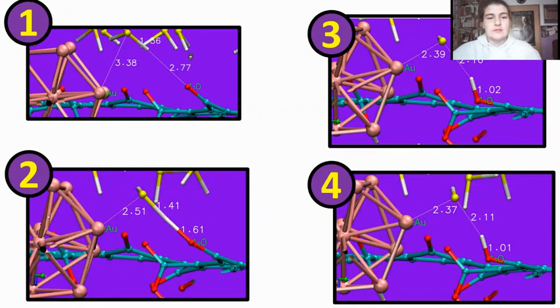Here are the snapshots from the movement. And so you can see that the bond between the sulfur and the hydrogen gets longer until the hydrogen bonds with the oxygen. And this is a very interesting transition, which will be subject of further investigation. And that leads us to the conclusion on the next slide, please.